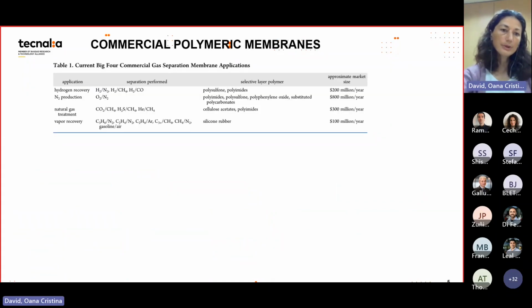So going more deep into different commercial applications that are today, like state of the art, we can speak about hydrogen recovery in different separations, like syngas or hydrogen from nitrogen. And here we use polymers which are glassy, polysulfone and polyimides mostly. Nitrogen production or air separation basically with membranes is mostly done with polyphenylene oxide. Natural gas treatment is done with cellulose acetate or polyimides, and vapor recovery is done with rubbery polymers.